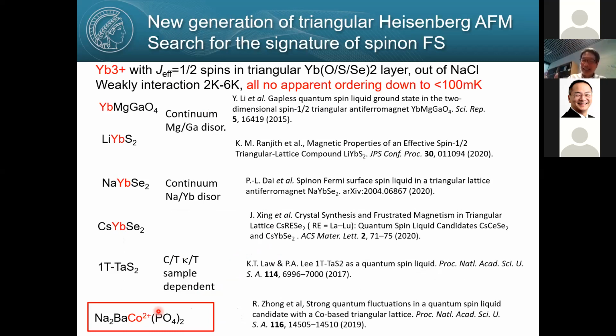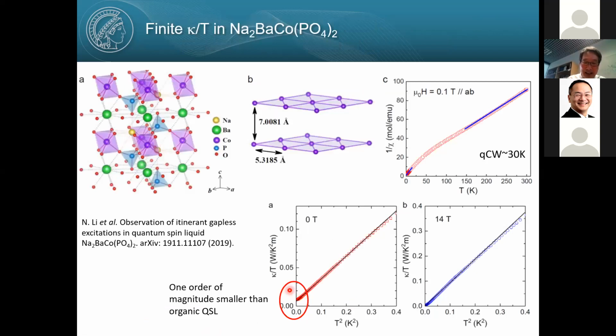It's great that we started discussing continuum excitation and spinon Fermi surfaces, but because of disorder, it's quite hard to identify continuum excitation. And of course, other compounds with a similar structure are claimed to be quantum spin liquids. In some cases they observe the continuum, but still we cannot completely rule out the possibility of disorder. Maybe this compound, recently proposed, cobalt 2+ with J=1/2, discovered by Bob Cava. They find finite kappa over T for this compound, suggesting itinerant excitation in the insulator. So in that sense, it might represent the best compound, but unfortunately, nobody has done neutron inelastic scattering measurements on this compound yet. So that's the situation.